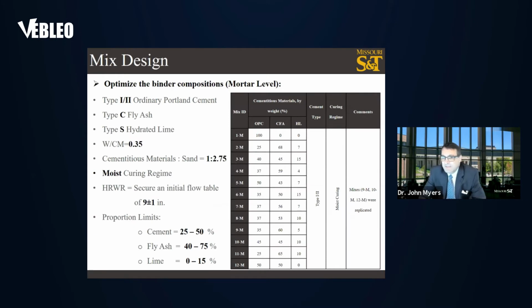As I just mentioned, the mix design went through 2 phases. The first phase was to optimize the binder composition, and through this phase, the cementitious materials were combined and generated using Design-Expert software. So 3 different materials were utilized: Portland cement, type I and II, type C fly ash, and type S hydrated lime. And within the use of the software program, a series of trial mixes were developed with ranges in the cement usage, the fly ash range, as well as the hydrated lime.